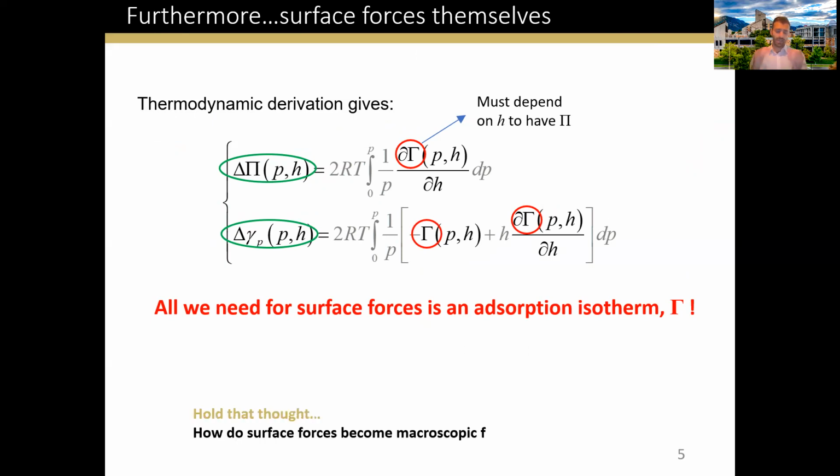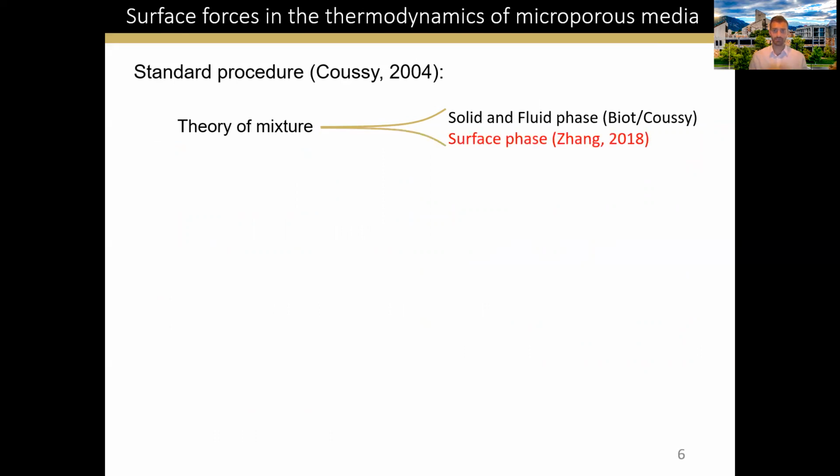But hold that thought. How do the surface forces on a pore level upscale to the continuum level to be incorporated in a pore mechanics framework? We follow standard procedure. The pore mechanics framework developed by Biot and Coussy takes only a solid and fluid phase into consideration in a theory of mixture. Zhang extends that theory by considering a surface phase in addition to the solid and fluid phase in the theory of mixture, and develops a so-called surface pore mechanics framework.